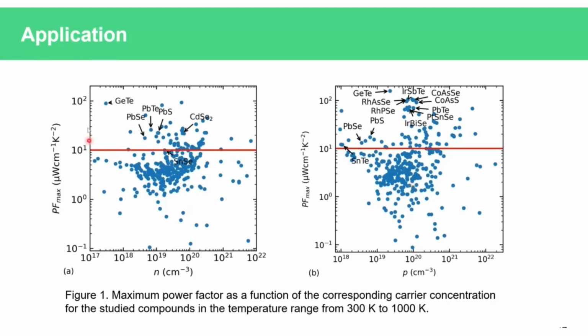These two pictures summarize the results, left for N-type, right for P-type. The y-axis represents the maximum power factor a compound can reach in the temperature range from 300 Kelvin to 1000 Kelvin. The x-axis represents the carrier concentration corresponding to this maximum power factor value. The red line means power factor value equals 10 microwatt per centimeter per Kelvin squared. Above this line, compounds are considered promising and go forward to calculate their lattice thermal conductivity and figure of merit.